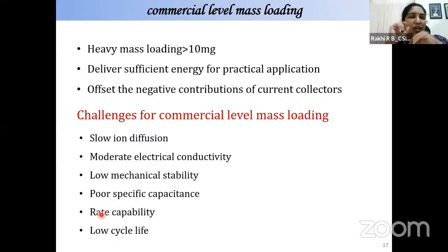But with the conventional way, if you go for commercial level capacitor making, that is just making a slurry, pasting, and coating on a substrate, there are some challenges associated with that. The electrolyte diffusion will be very slow and there will be moderate electrical conductivity. Only if the top level is exposed, the other levels are not exposed, and it can be brittle. So no mechanical stability, poor specific capacitance.